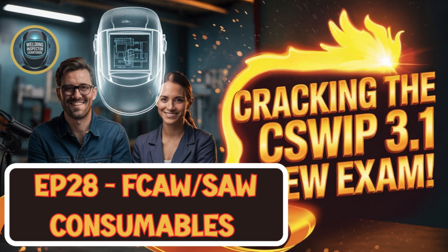Exactly. It's highly concentrated precision chemistry. The power in that powder comes down to specific core elements and their functions. For instance, you'll almost always find silicon and aluminum in there. Their main job is deoxidizing and denitrifying the weld, which means they effectively scavenge or grab onto any harmful oxygen and nitrogen impurities, which, if left in the weld, could cause brittleness or porosity. Okay, so they're like little cleaners.